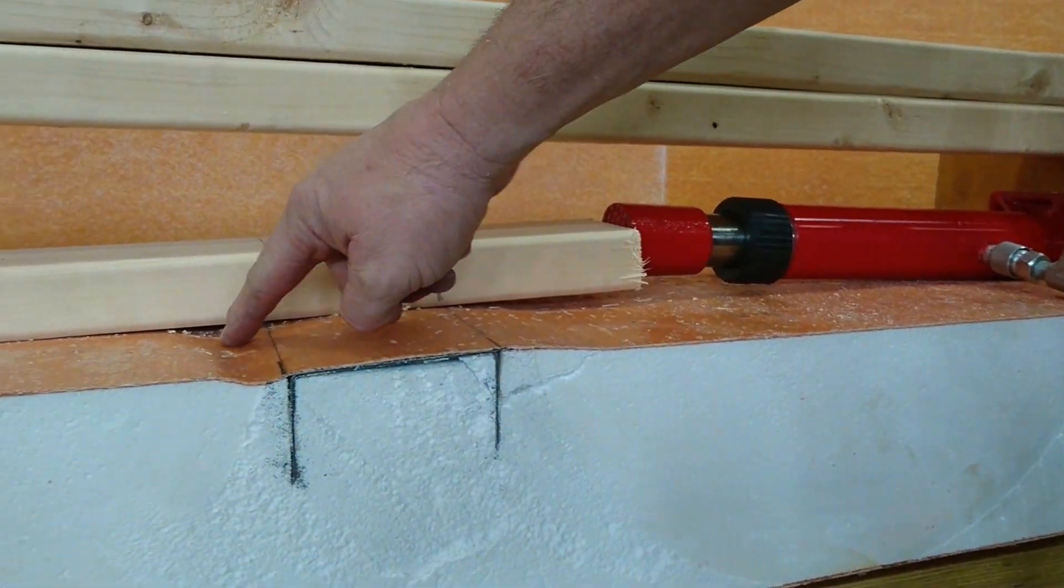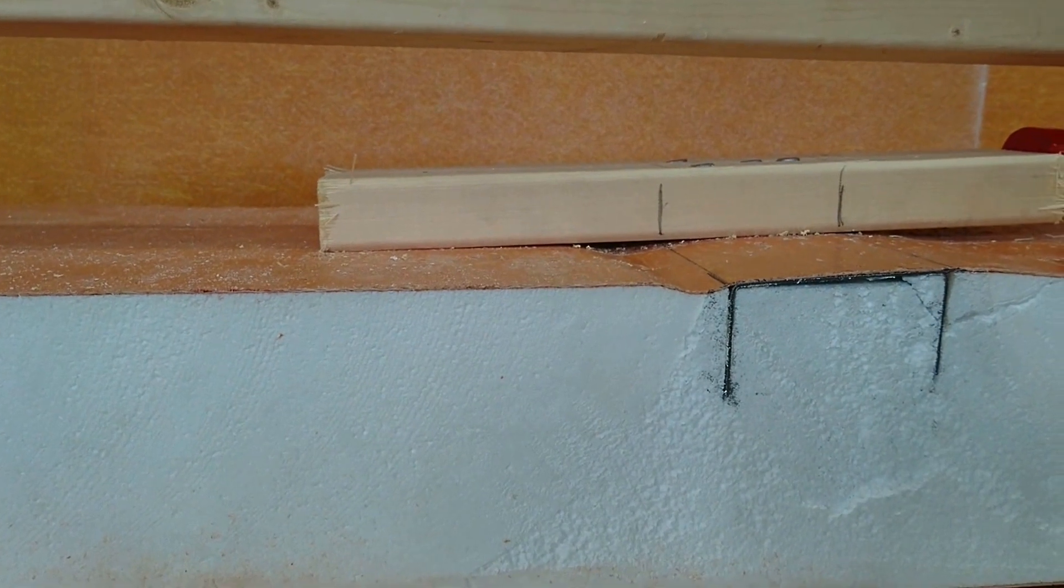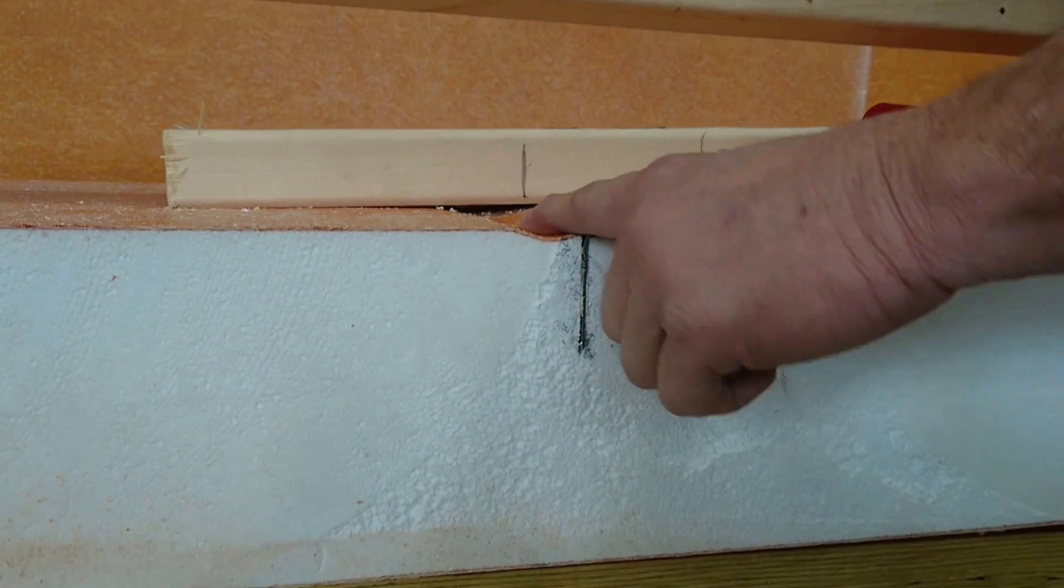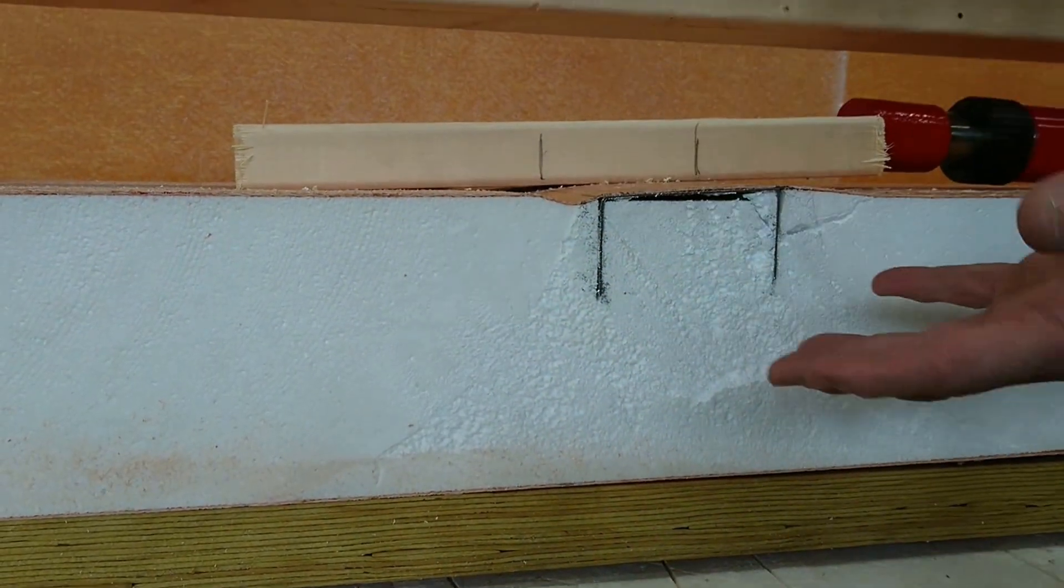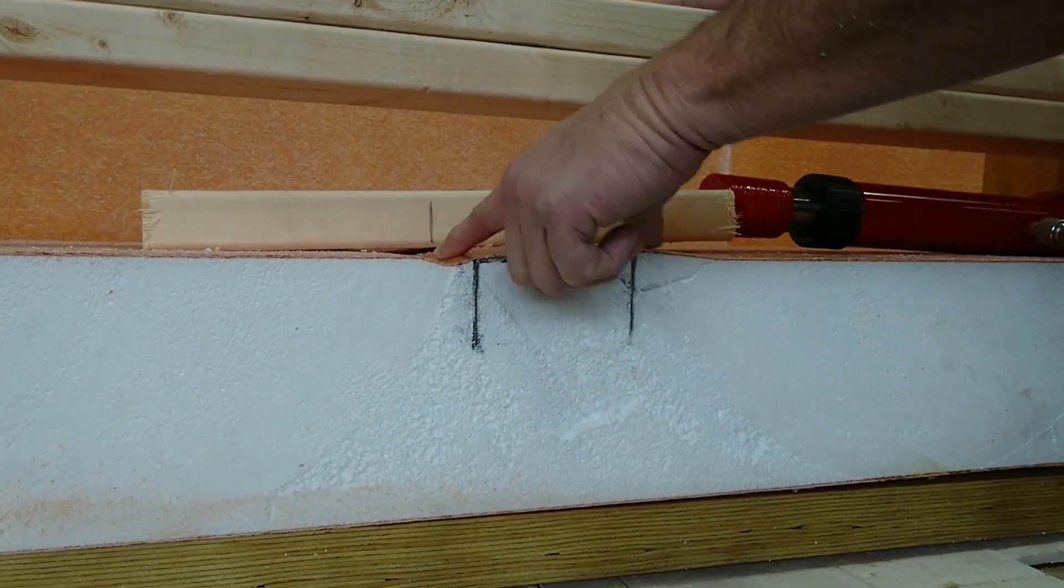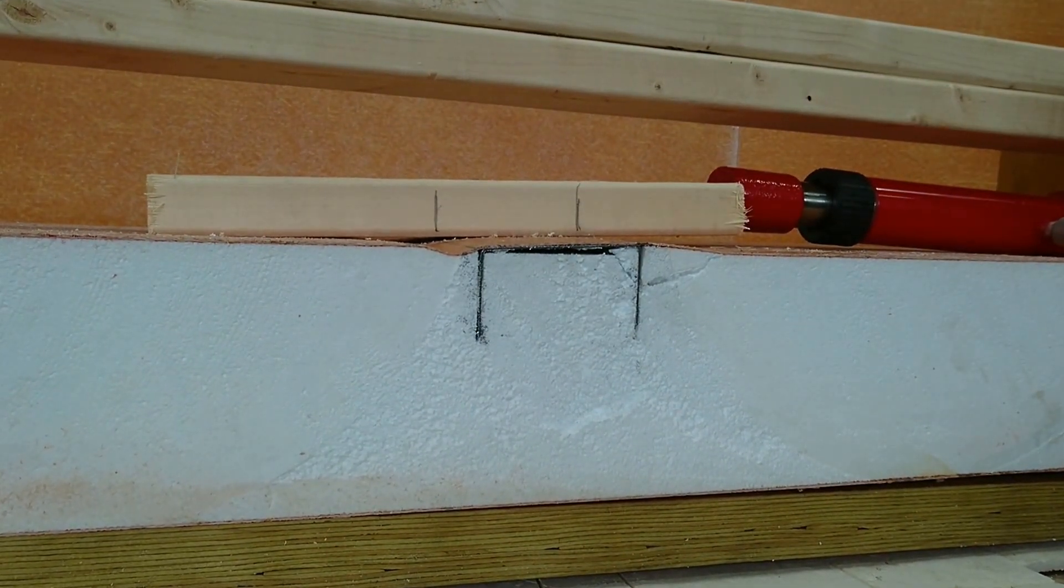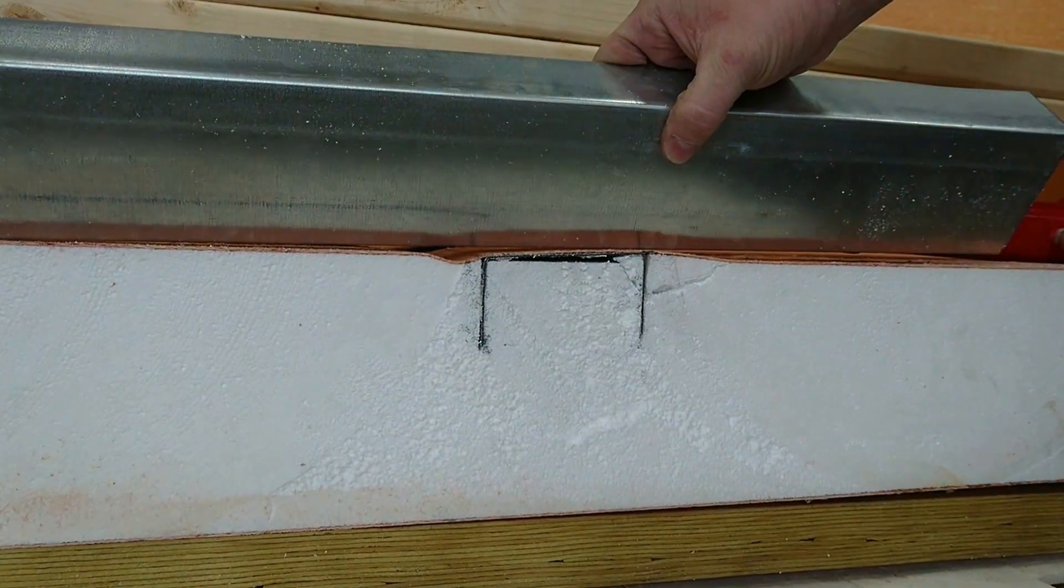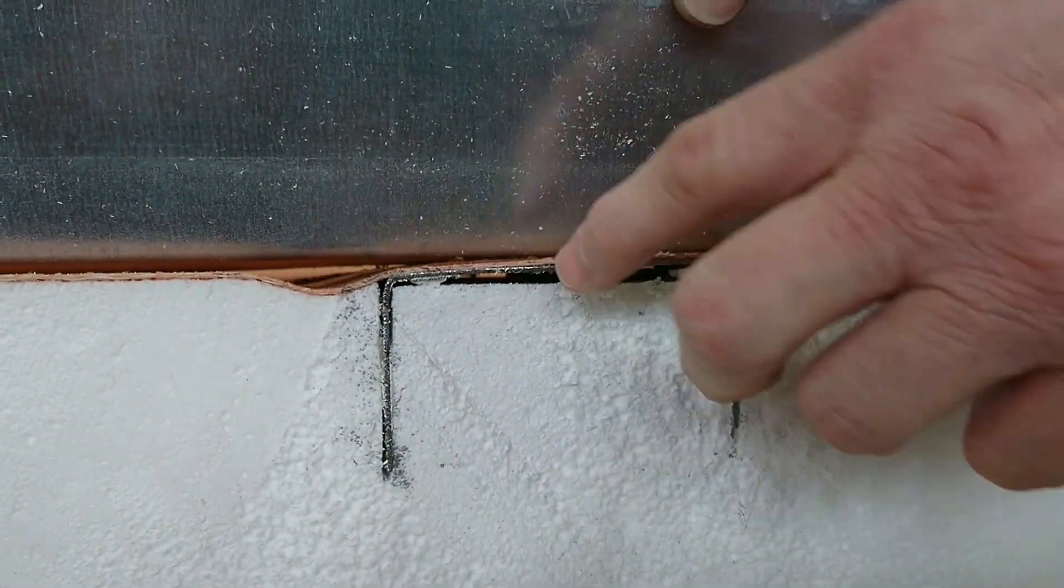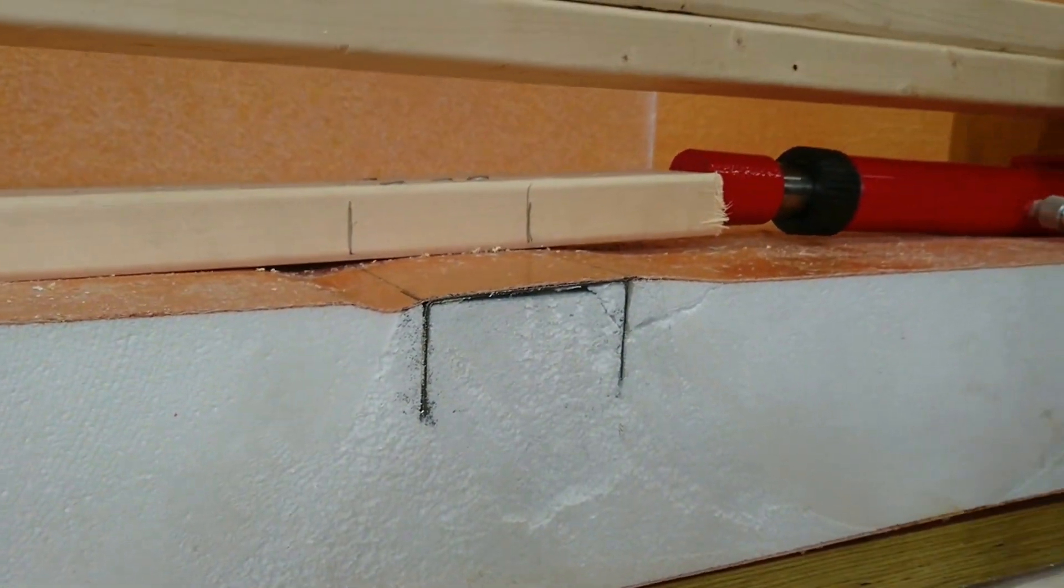Yeah, and right now we're starting to buckle. What we're getting here is a buckling failure where the skin is actually buckling in on itself, which is typical of how a composite panel is going to fail because this side down here is in tension and this side is in compression. We're twisting this panel this way, which is causing this buckling failure right here, right at the point of all that weight. And you can see if we put a straight edge across there, you can see pretty plainly what the shape of the panel is there. We can see here's where it cracked yesterday, and here's our buckling failure here and everything's just twisting this piece of steel around in there.